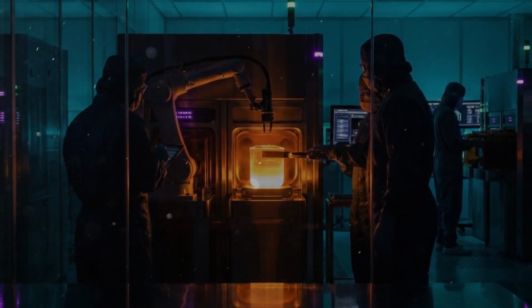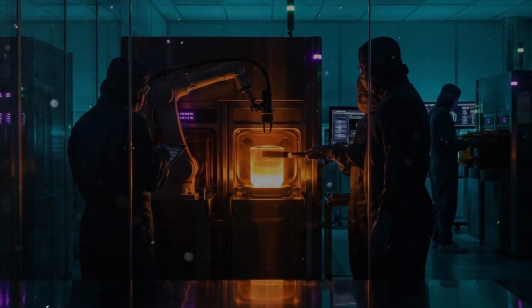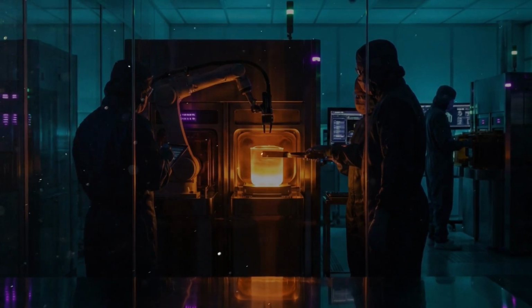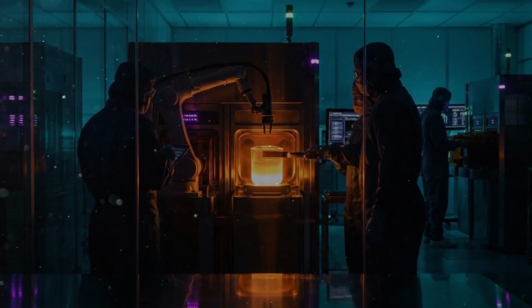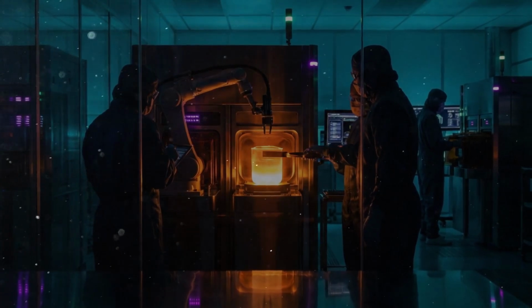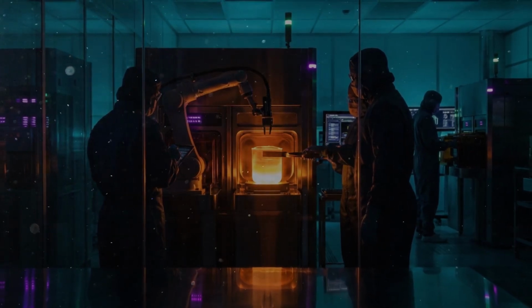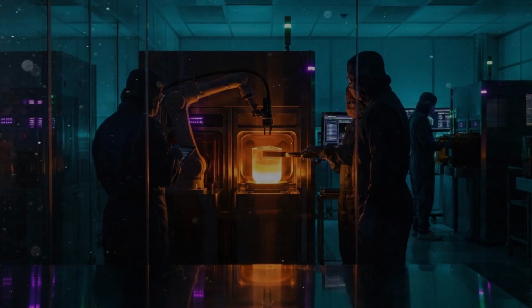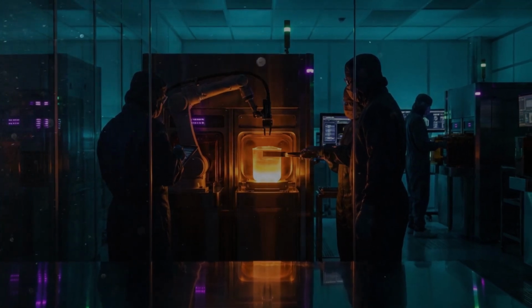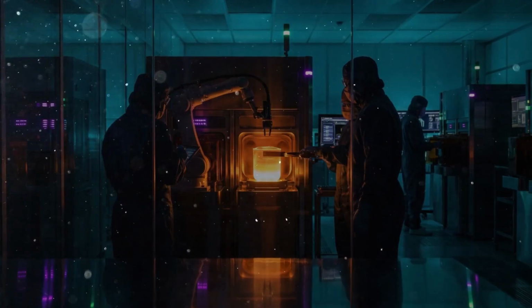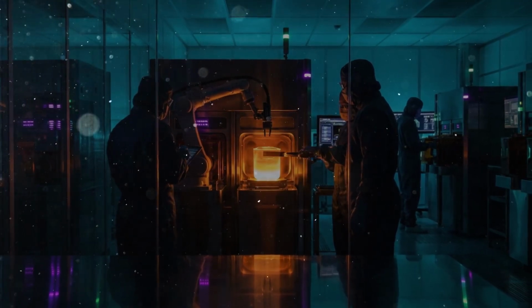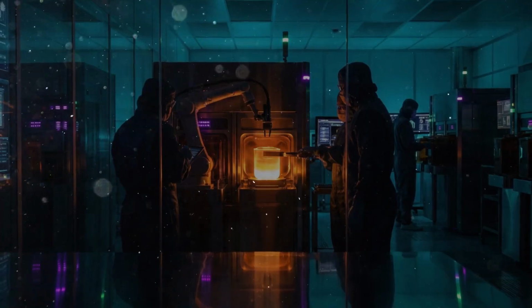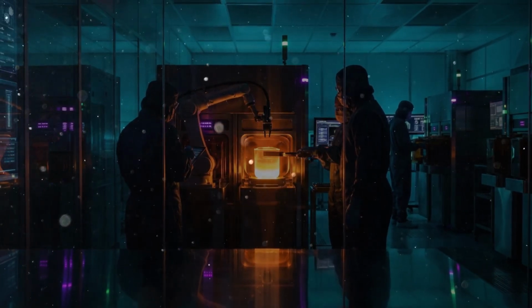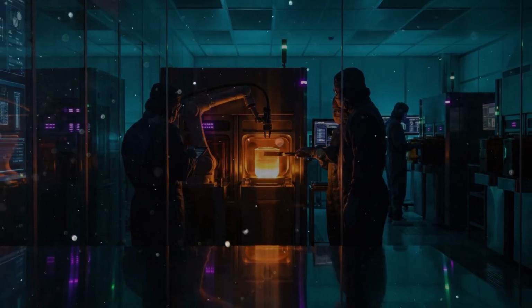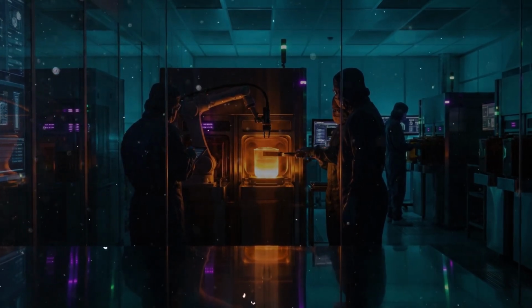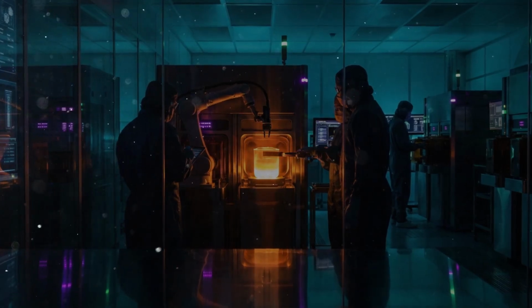Fused quartz can withstand continuous operating temperatures up to 1150 degrees Celsius, making it ideal for laboratory glassware, telescope mirrors, and high-temperature industrial applications. The thermal expansion coefficient of quartz is remarkably low, about 0.00000055 per degree Celsius. This means quartz barely expands when heated, a property that contributes to its stability in oscillators and its usefulness in precision instruments.